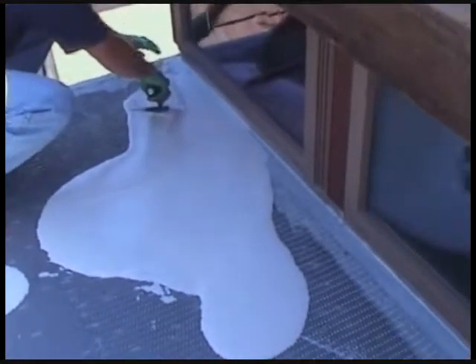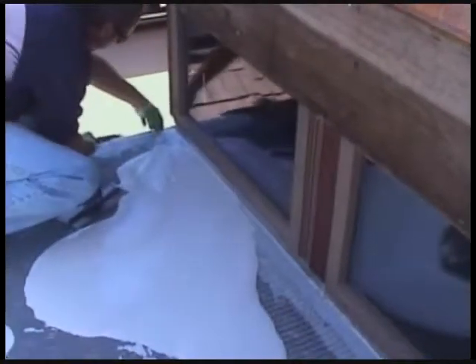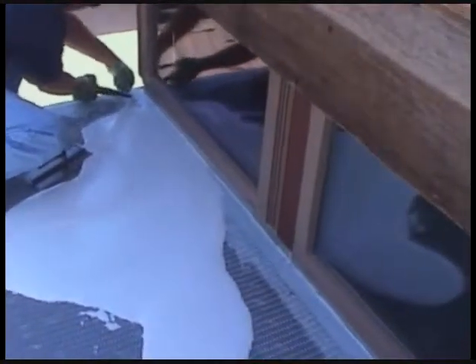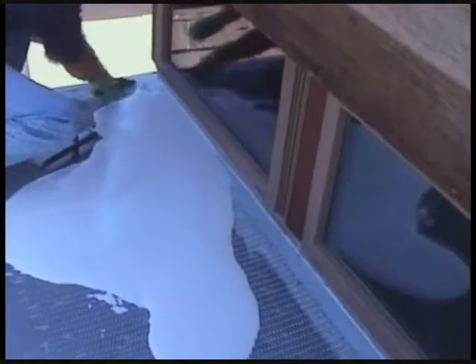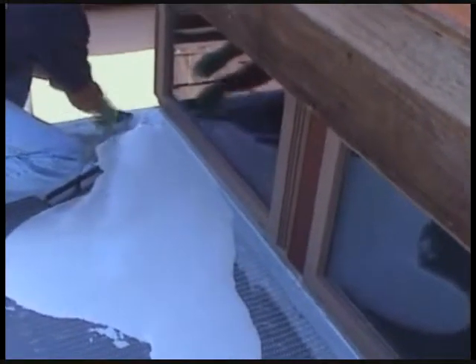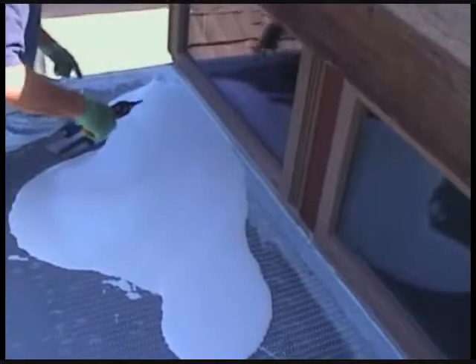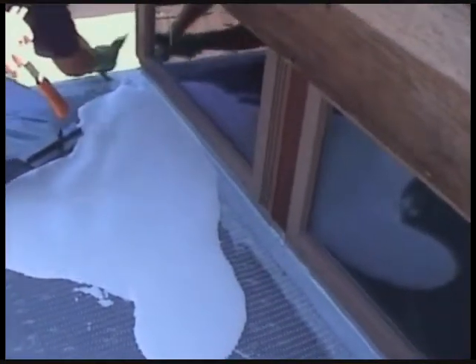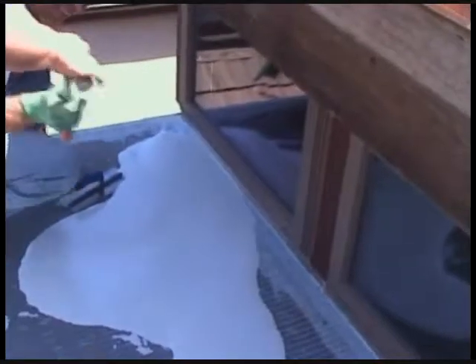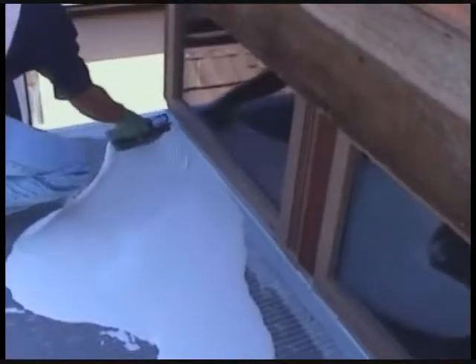Contractor found an area here where the metal lath was still sticking up, so he's trimming it down. It's important to nail the flashing. Make sure that the flashing and the metal lath is completely stapled down around the perimeter of the deck and around the perimeter of each piece of metal lath.